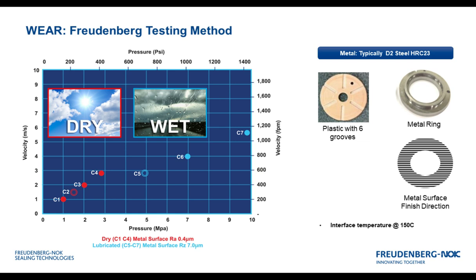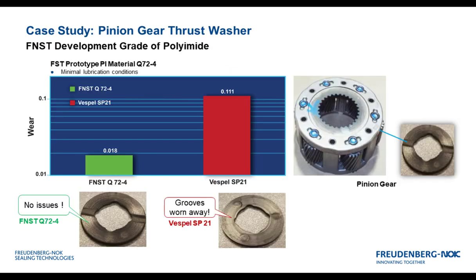So if the condition in the application really runs more towards the dry side versus the lubricated side, that's where we'll have to know, because if we don't understand the application lubrication conditions, we could see an unexpected failure mode, because you move from one failure to the next. But we have correlated that. I mentioned the slide earlier, but on the slide I'm calling up now, the slide on the pinion gear, this is an example where we validated the actual part performance to the actual wear test method.